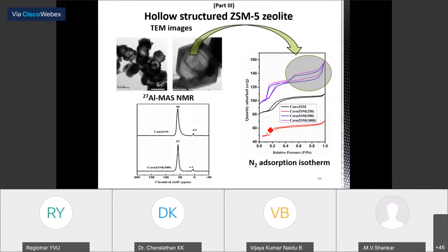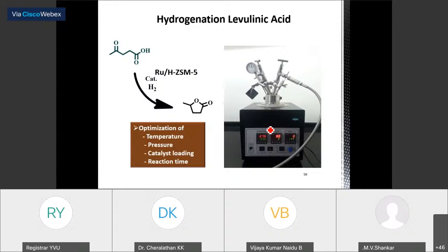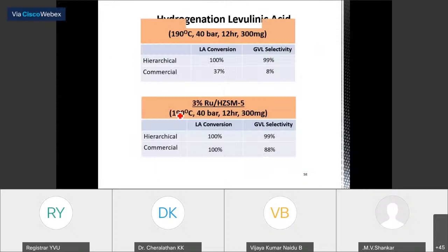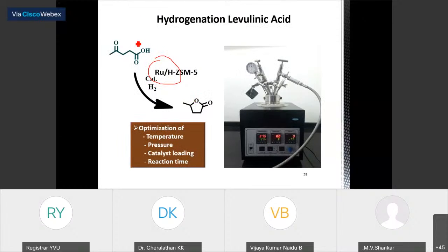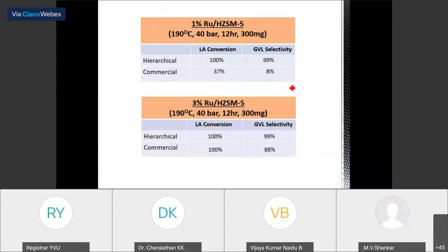So like this, we also prepared hierarchical zeolites, and we found that with ruthenium, this hierarchical zeolite is performing better than commercial zeolite. This is a hydrogenation reaction. We try to hydrogenate this carbonyl group, and then it will undergo lactonization and form this lactone. This is called gamma-valerolactone. It has many applications. It can be used as a fuel as well as a solvent. So we got 100% conversion and 99% selectivity of this product.